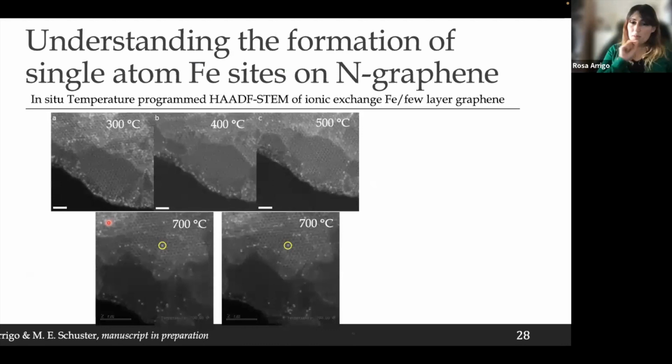Now, in this system that I have shown you, unfortunately, we have a large distribution of iron species. We found the bulk iron oxide hydroxide doesn't change upon polarization, so we can exclude that component. But then we still have the chain at the edges, and we still have the single site. So which kind of iron species is relevant? That was the next question.